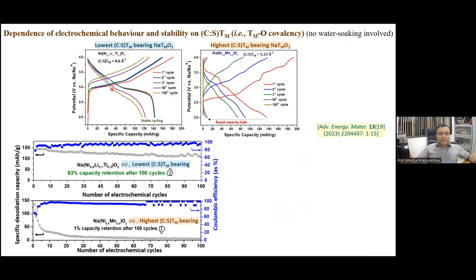Now, let us look at the cyclic stability. These materials have not been exposed to air or water. They have been kept inside the glove box right after the synthesis, so no air or water soaking as such. But still, interestingly, we see that the lowest charge to size ratio bearing material, which was water stable but of no relevance here, exhibits much better cyclic stability as compared to the highest charge to size ratio bearing material. So this charge to size ratio of the transition metal slab not only influences the air and water stability, but also influences the electrochemical cyclic stability.